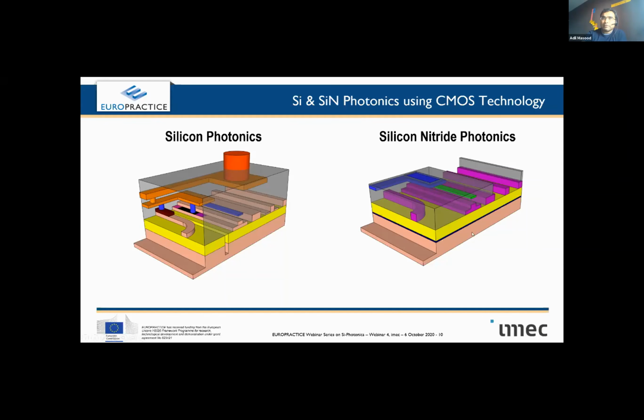So what is there at the bottom is a silicon wafer, or let's say silicon substrate. Of course, it is way thicker. It's typically 600, 700 micron, while the stacks above it are just a few microns, so not to scale. And then with the deposition of oxide or other materials, let me first focus on just what is common between these two stacks. Silicon substrate at the bottom, followed by silicon dioxide layer.